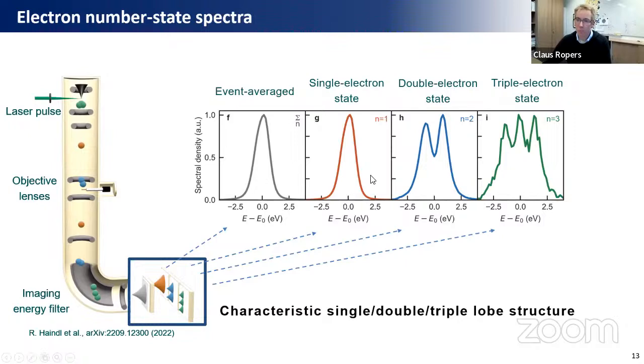But if you only plot the electron energy distribution of the 2 electron events, there's a drastic change in the spectrum, and the spectrum develops into a 2-lobed structure. Yeah, which already might tell you that there's actually an interaction of these 2 electrons. You can't emit 2 electrons at nearly the same energy; they're actually repelling each other. But the interesting question is, why are they repelling each other to such high energies? Because this would indicate that the electrons are actually emitted from a very, very small volume, much smaller than what we would have expected from the size of the source.